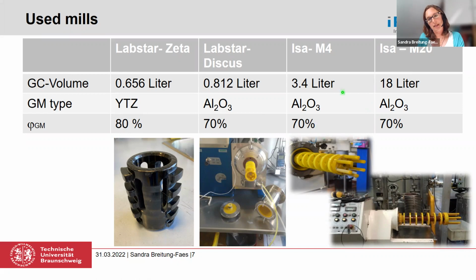And then we have an ISA mill available at the Institute, and we were able to use an even bigger ISA mill at the Bitossi company. And here 2 master theses were run to grind dolomite, also with alumina beads. In principle, you can see they look very similar. They are only different in size. They have discs with holes inside, and these pins at the end as separation unit for the grinding beads. Okay.